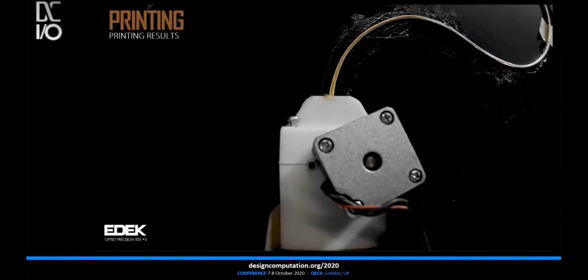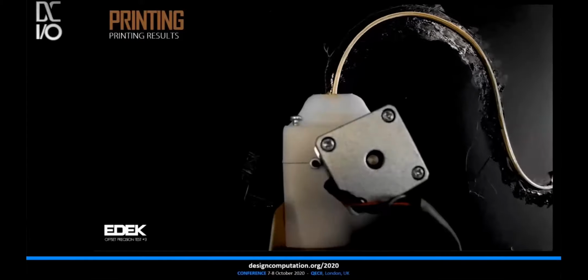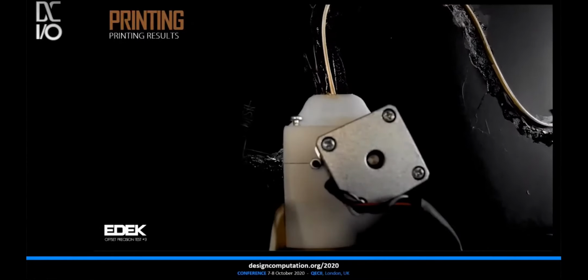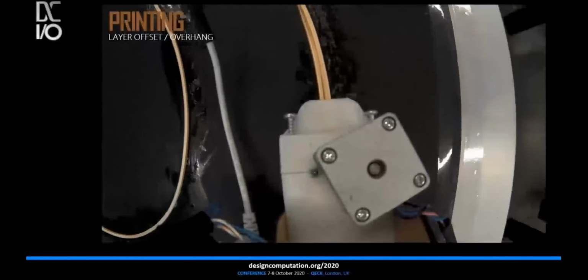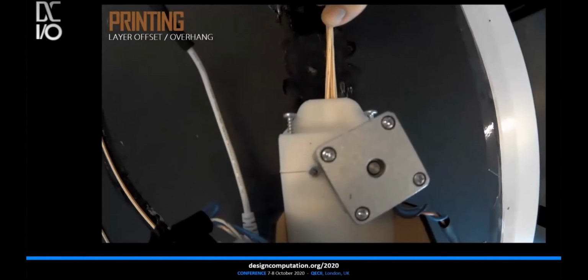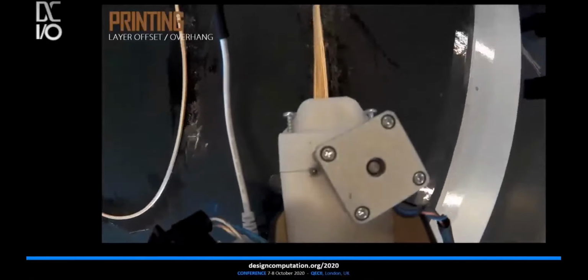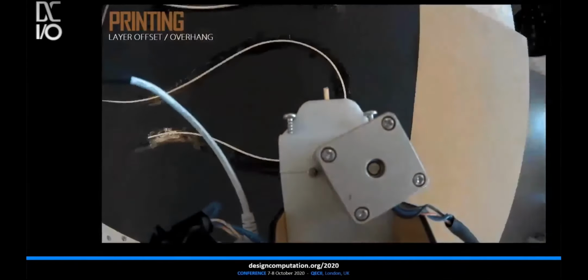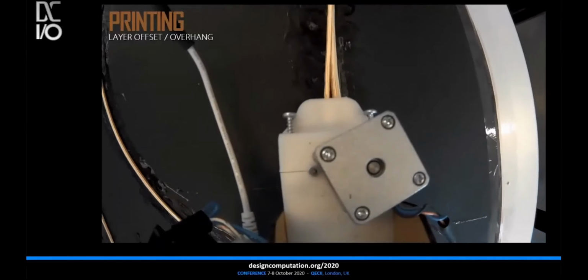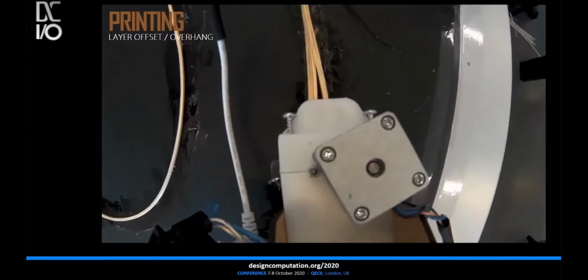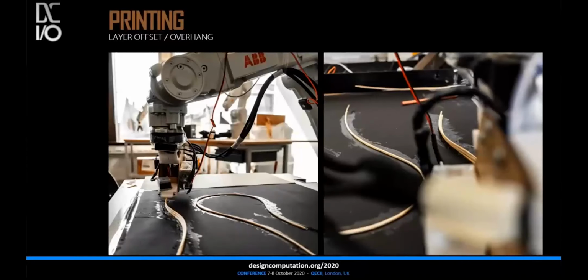A greater angle led to a twisting behavior of the extrusion that drastically reduces the accuracy while printing. Four layers were printed on top of each other with an increasing offset to test the overhang capabilities. An overhang angle of 22.5 degrees was saved as a maximum parameter to print solid shells. Now we have seen the potential of printing with solid wood.